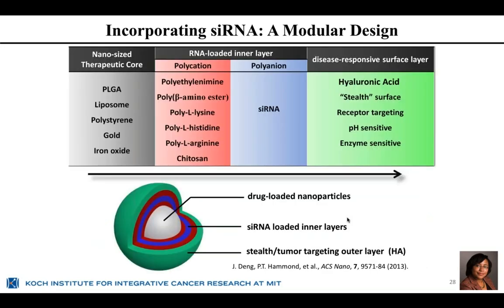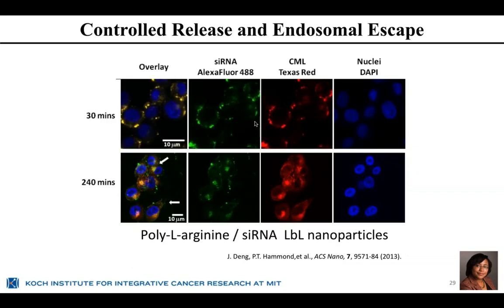Finally, of course, we have to incorporate our cargo, and our cargo is siRNA, which is going to silence one of the genes that allows these tumor cells to avoid death. And to do this, we had to optimize against a range of different polycations. And this is a short list of some of the polycations that we used with our siRNA. And we looked at loading, but we also looked at whether or not we were introducing toxicity to the nanoparticle. And it turned out that poly-L-arginine, a simple homopolypeptide, is a great system for not only incorporating the siRNA in sufficient amounts, but allowing us to get the nanoparticle both in the cell and out again from the endosome into the cell cytoplasm, where siRNA can be translated.